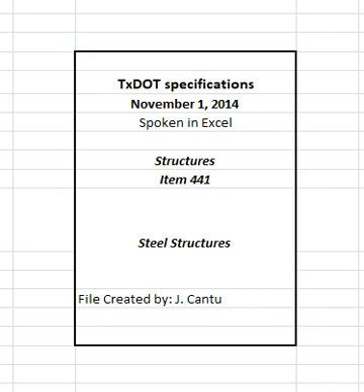Remove from all unpainted weathering steel fascia surfaces, see section 441.3.8.2, weathering steel, any foreign material, including markings, that adheres to the steel and could inhibit formation of oxide film as soon as possible. Feather out touched up areas over several feet. Do not use acids to remove stains or scales.